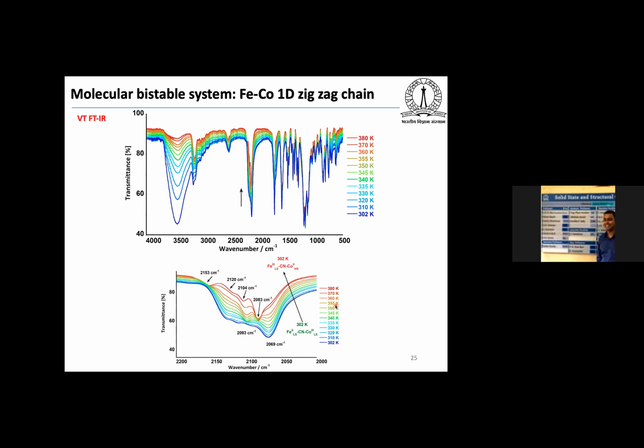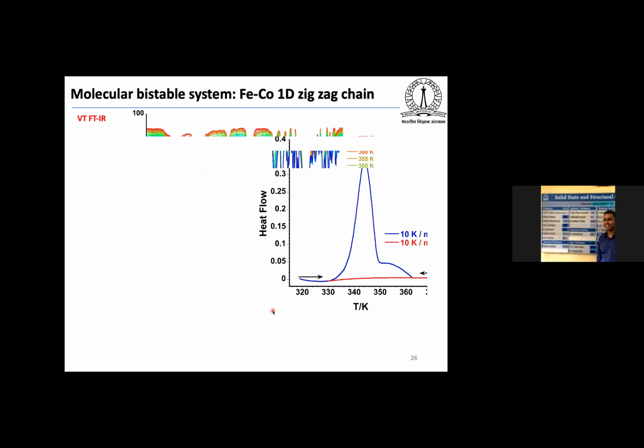So you can see when you increase the temperature of the system above 355 Kelvin, there is a peak coming around 2153 centimeter inverse, and when you decrease the temperature, this peak is vanishing. You can also see that the intensity of the 2069 centimeter inverse peak is vanishing when you increase the temperature. So that is also suggesting that electron transport is taking place in this center at high temperature.